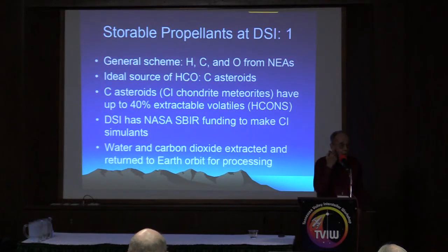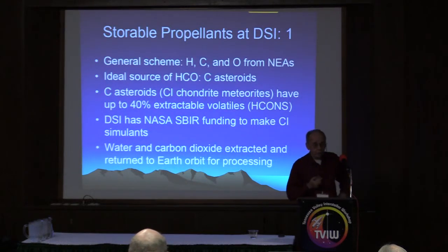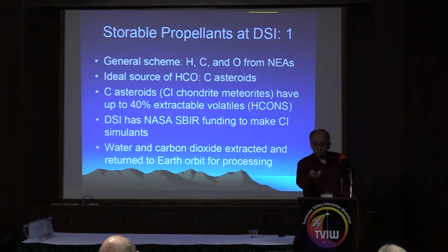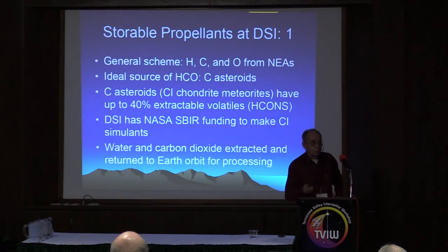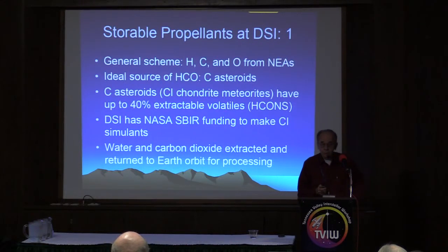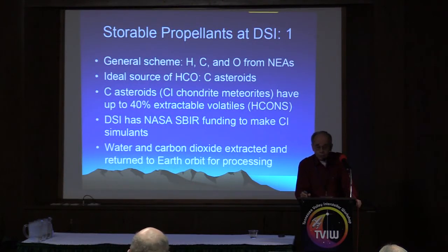We've been concentrating, for the sake of filling in a gap in our understanding, on the manufacture of storable propellants in deep space industries. The general scheme is to extract hydrogen, carbon, and oxygen from near-Earth asteroids as water and CO2. The ideal source among meteorites is the carbonaceous asteroids, the C-type asteroids. The C-type asteroids, carbonaceous chondrites, CI chondrites, type 1, contain hydrogen, carbon, nitrogen, oxygen, and sulfur to the extent of up to 40% of the total mass of the meteorite.